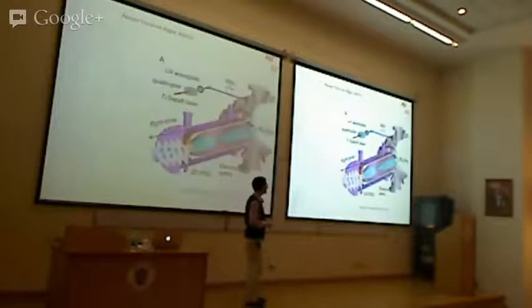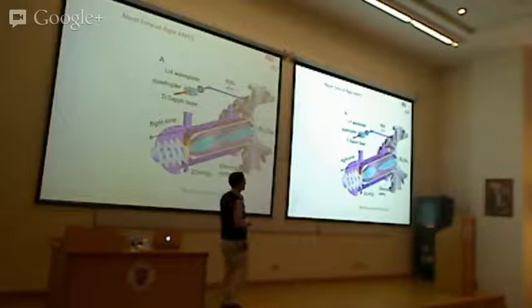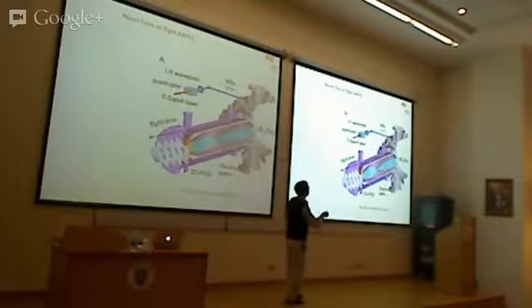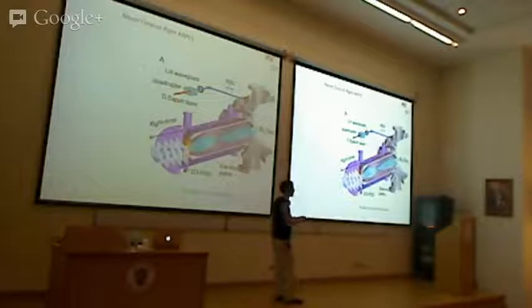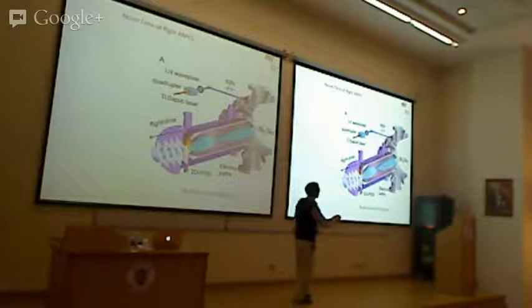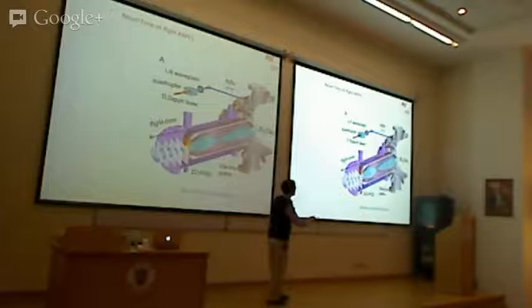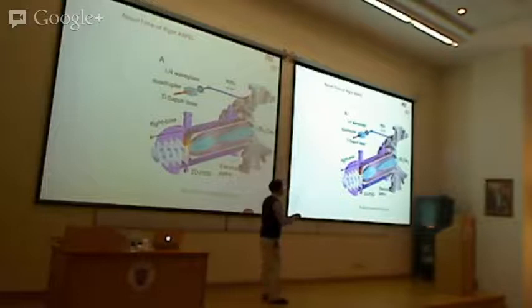Our detector is very different — we have a time-of-flight tube, about a meter long. We use a laser pulse at 1.5 eV, quadruple it to generate the fourth harmonic at 6 eV, above the work function. This pulse ejects electrons from the sample. Because it's a short pulse, the ejected electrons have a well-defined ejection time. We measure the time it takes for electrons to reach the detector to get their energy, and use a two-dimensional delay-line detector to get both Kx and Ky positions simultaneously — no need to rotate the sample.